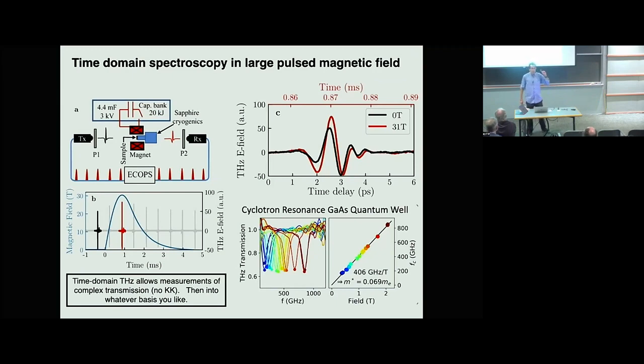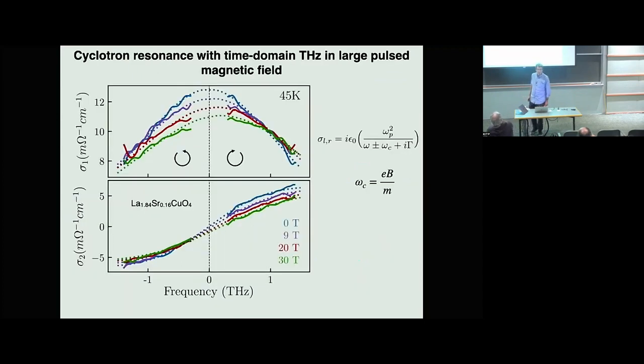Another point that I'll make, and this will come back on the next slide, is that time domain terahertz spectroscopy allows measurements of the complex transmission functions. So there's no Kramers-Kronig transforms or anything that needs to be performed. We measure in a polarized fashion, and having measured the complex transmission functions, we can transform the data into whatever basis we like. We could have X and Y, which typically is more complicated for these kinds of experiments. And we like thinking of it in terms of right and left circularly polarized light. And so that's the data right here.